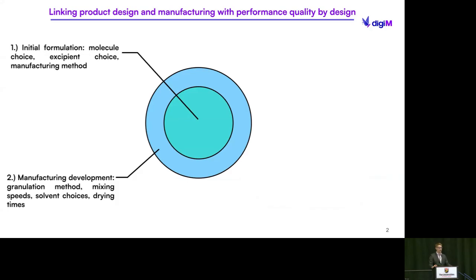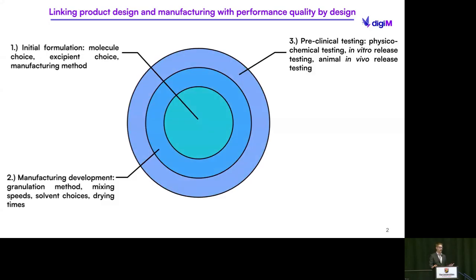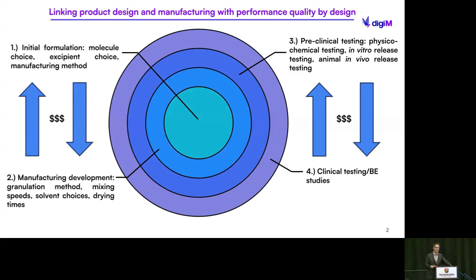Coleman did a wonderful job of highlighting some of the challenges that go into that with Ozurdex. You extrude twice and then lead to that. Finally, you have your preclinical testing, your physicochemical, your DSC, your FTIR, as Michael was highlighting, in vitro release, and potentially in vivo release if you can. And then finally, BE studies, where we've highlighted a lot of times that in the case of ophthalmics, a true BE study that might be done for oral solid is really not on the table.